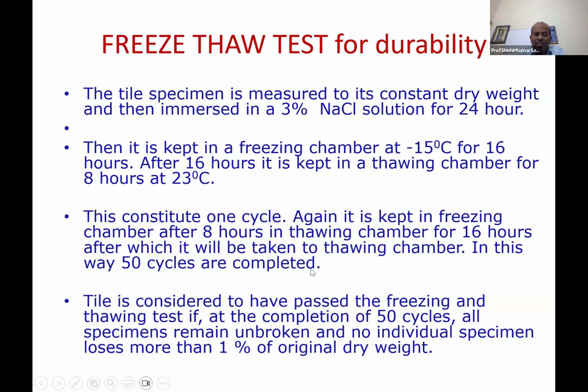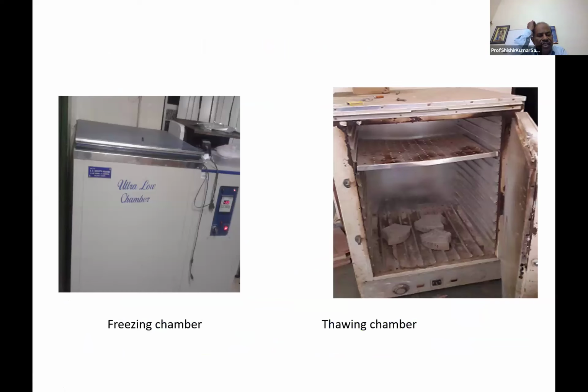After 50 cycles, specimens are tested. A tile is considered to have passed the freezing and thawing test if, at the completion of 50 cycles, all specimens remain unbroken and no individual specimen loses more than 1% of the original dry weight. That is the code criterion, and that is satisfied. This is the freezing chamber. This is the thawing chamber.